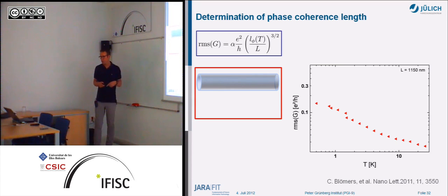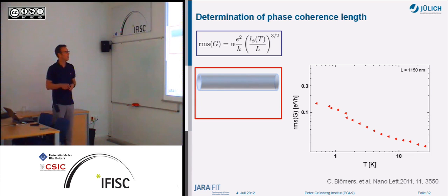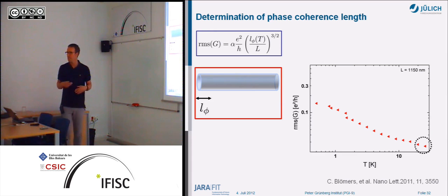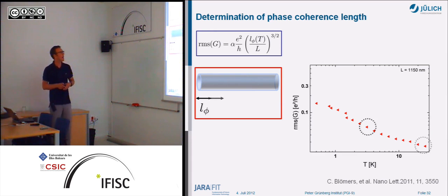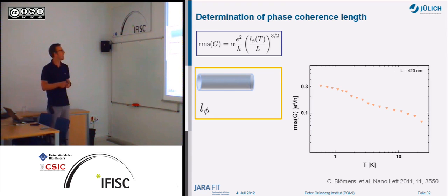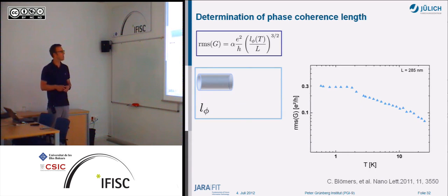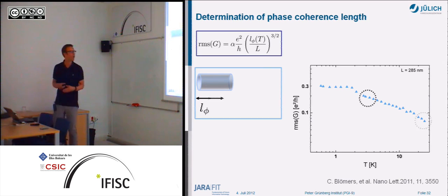And that's the result. If you look in detail, what is plotted here is the fluctuation amplitude, the root mean square, as a function of temperature. If you have a long wire, then the phase coherence length at large temperature is short, so then we have a lot of inelastic scattering in between. We have no ideal case, so everything is determined by the phase coherence length here. And if we increase the temperature, the phase coherence length decreases, and then the RMS is decreasing as well. You can observe this, and also if you have a shorter wire, it's the same. Here we have a phase coherence length shorter than the nanowire, and if we decrease the temperature, it's getting longer, but it's still in the order of the nanowire.